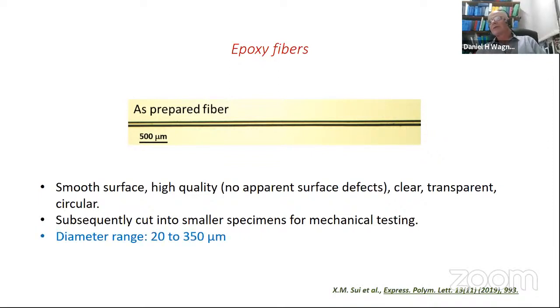The range of diameter that we were able to prepare in this first set last year, or 2 years ago, was between 20 and 350 micron, which is smaller than anything else that actually exists in the literature, including those other papers.